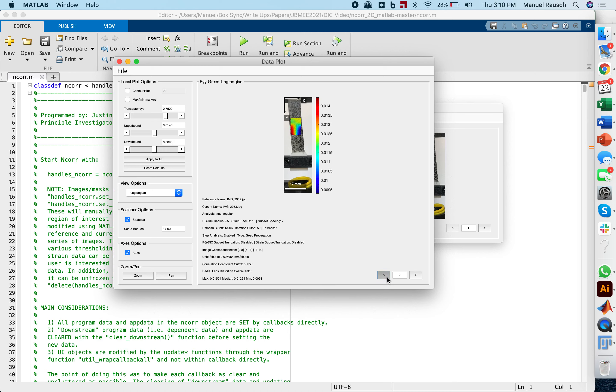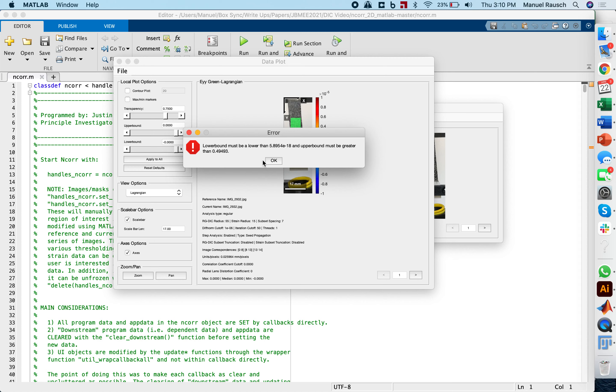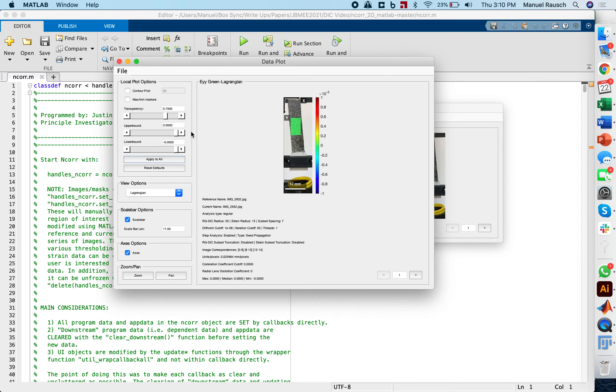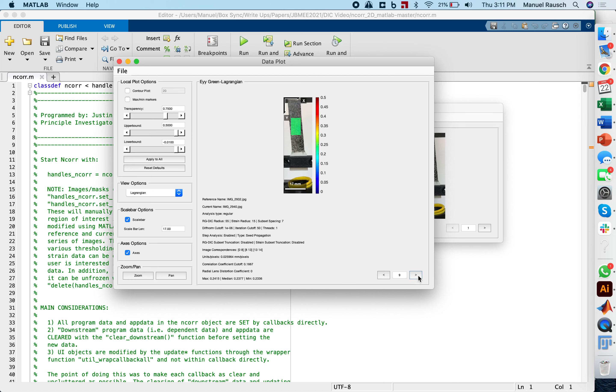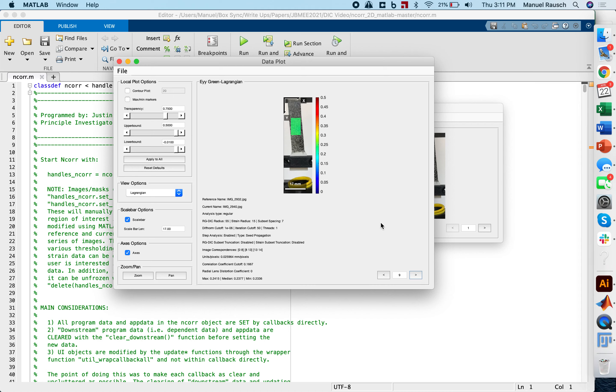So what I found works is I go to image two. I set the lower bound as something like minus 0.01, the upper bound as 0.5 and then apply this to all. Unfortunately, we're getting an error here. It never quite seems to work for me. Okay, we set this to 0.5, this to minus 0.01, and then apply to all. Okay, that worked. So in your reference configuration, of course, you have zero strains. And then now on a global scale, you see that the strains are actually quite homogeneous throughout the sample, given the global range of strains that we're looking at. And I just want to remind you all that the reason we picked a region far away from the clamps and we use the dog bone sample is to kind of create a homogeneous strain zone or region in the center of the sample, which we actually achieved here.